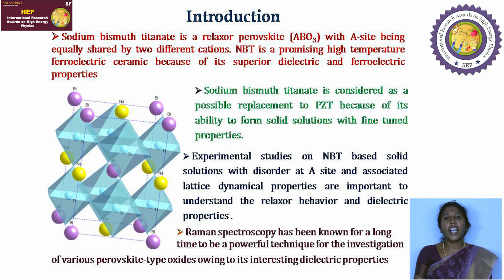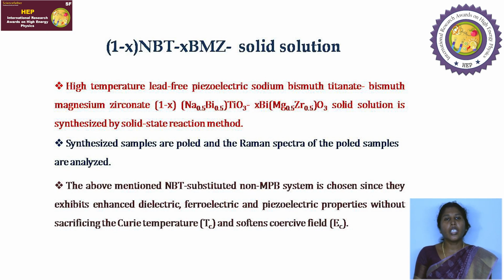Experimental studies on these solid solutions showed that because of the A site disorder, there is an associated lattice dynamical property that is important to understand the relaxor behavior, dielectric property as well as the ferroelectric properties. In order to understand the dielectric properties, Raman spectroscopy is a best tool for the investigation of the dielectric properties in perovskite type oxides. Now we are going to see about the NBT BMZ solid solution.